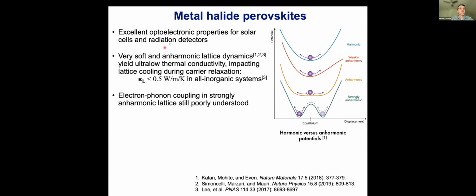They are crystalline, but very soft and strongly anharmonic, so very different from silicon. They have very low thermal conductivities and are actually candidate thermoelectric materials also for that reason. They also have very large thermal expansion coefficients, very large mean square displacements, very low elastic constants. And it's starting to be appreciated that these peculiar lattice dynamics are very likely important to understand the electron phonon